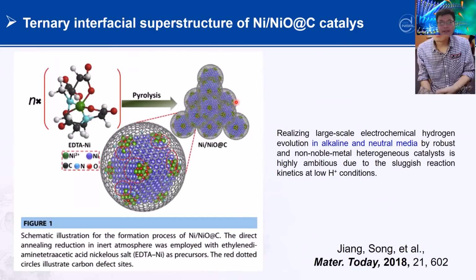So this is the first example. We tried to build some carbon with some transition metal. We selected nickel. We developed one process to make a very unique structure. In this unique structure, you can see we tried to use the carbon as a shell, which covers the nickel particle. But around the nickel particle, we will have nickel oxide, but not too much.